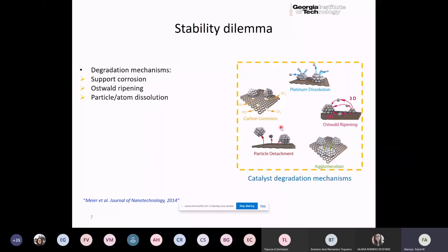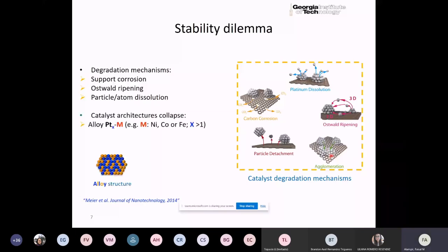You could also have the catalyst atoms, because the particles are small and the surfaces are very reactive. The reactive surfaces also make it easier for the catalyst to lose itself, corrode, right? And so taking the example of platinum, you can have platinum dissolution. There can also be physical detachment, right? And the support material itself can actually start to degrade. And finally, you can have particles combine and start to grow, not just through ripening, but through agglomeration. So all of these are effects that over time will lower the effectiveness of the catalyst by not making them stable enough against change. Catalyst has to resist change. That's one of the big prerequisites for a catalyst.